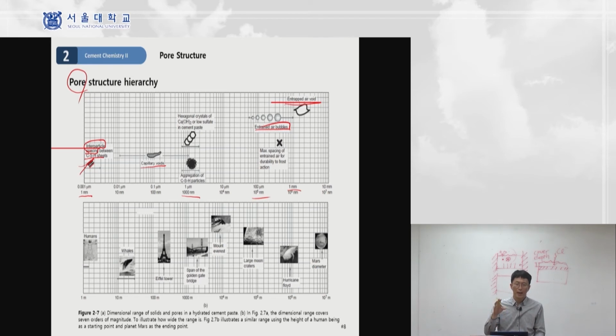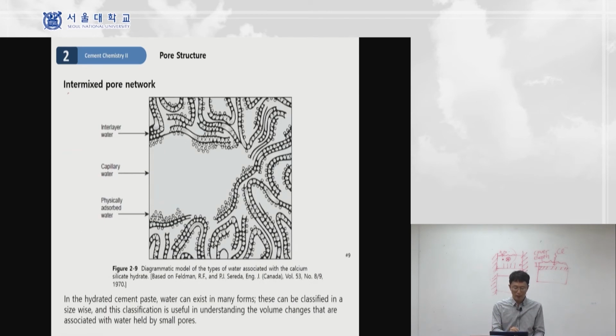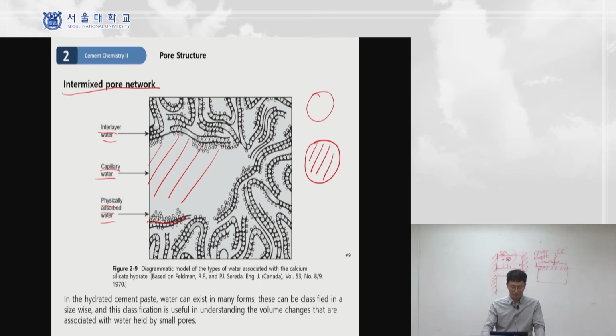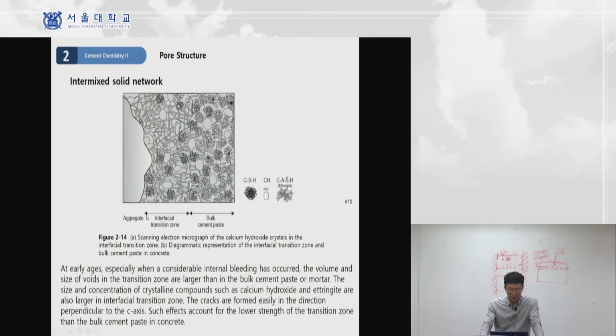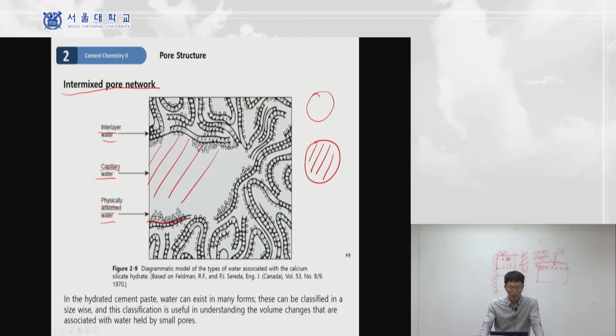So all of these make concrete application or concrete study complicated. Okay, so the pore has an intermixed pore network. There's interlayer water in the calcium silicate hydrate, physically adsorbed water on the surface of the calcium silicate hydrate, and also voids filled with water in the capillary pores. Like I mentioned before, we treat the water volume as a pore. Pores can be empty, but also can be filled with water. We treat both of them as pores. So there's the crystal structure solid network, and also the pore network.